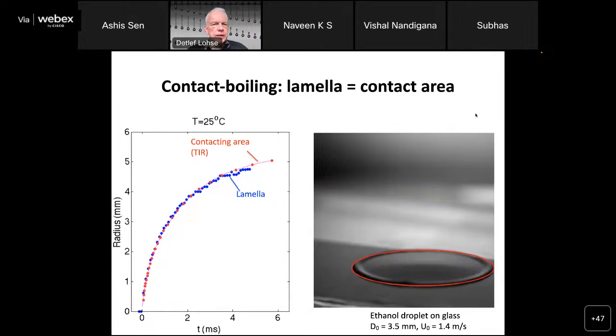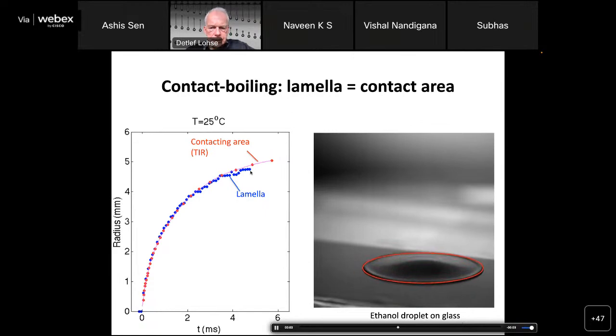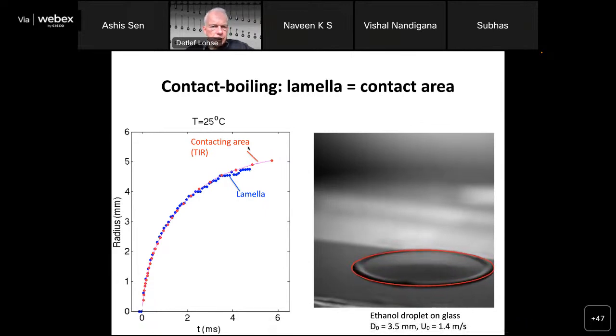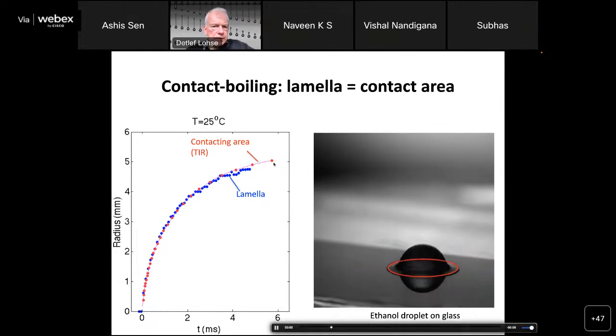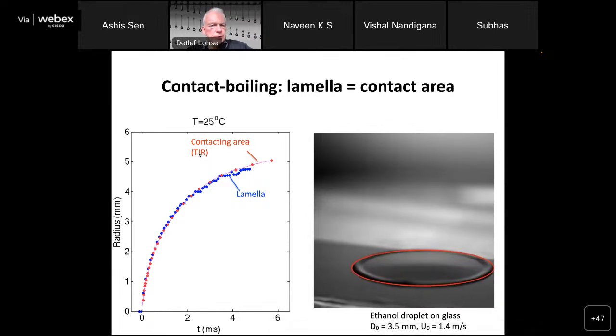And at 25 degrees, things are fully correlated. So from the side, we look at the lamella here, and from the bottom, we get these red data points. This is the contact area with total internal reflection. And at 25 degrees, this is just the same. What you see from the bottom is the same as what you see from the side.